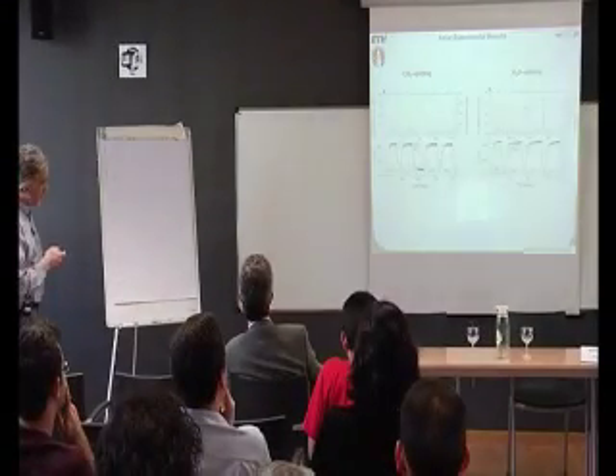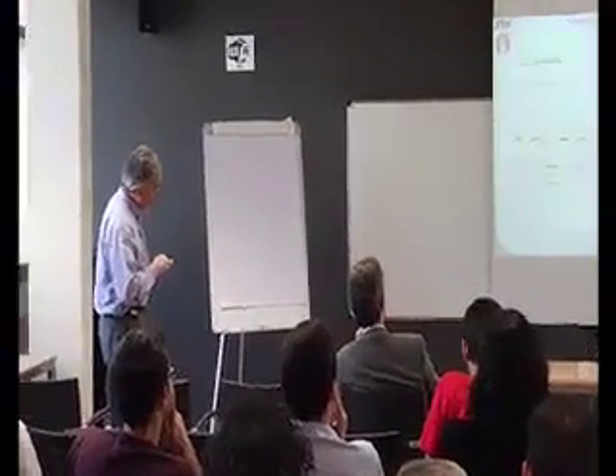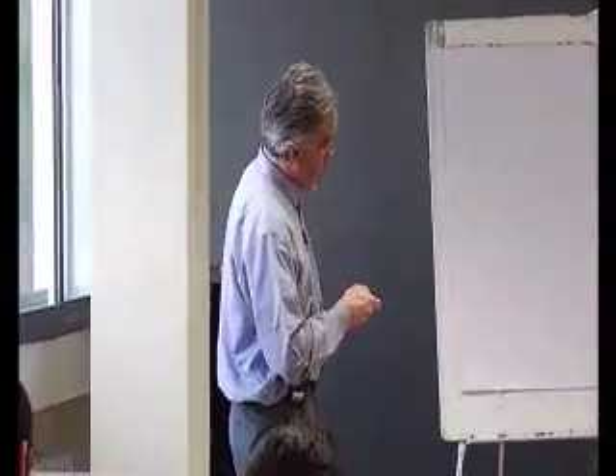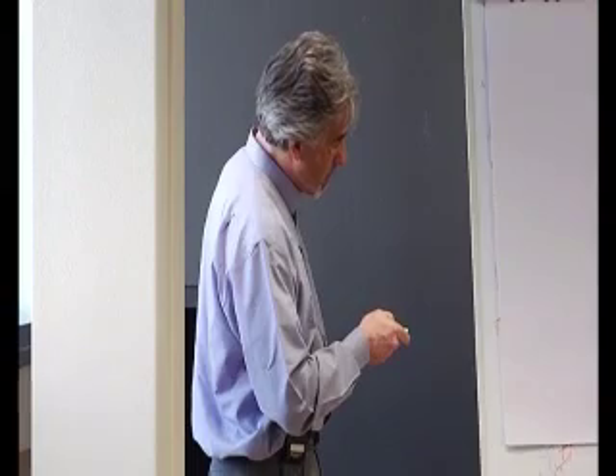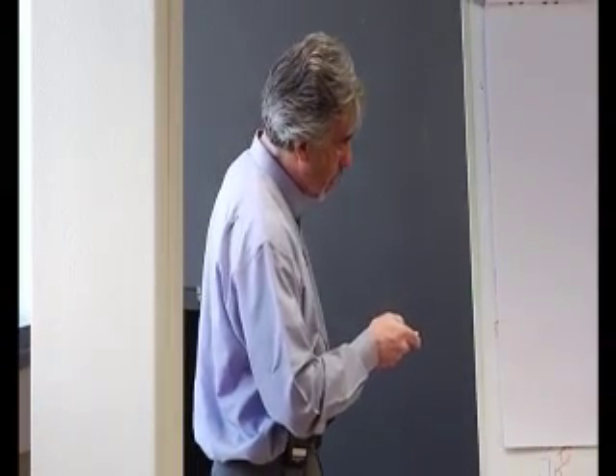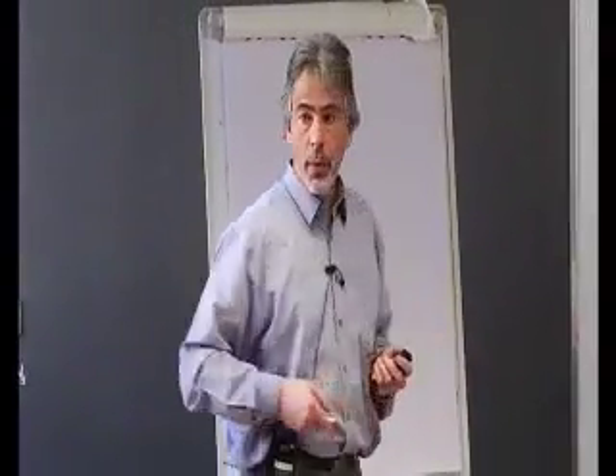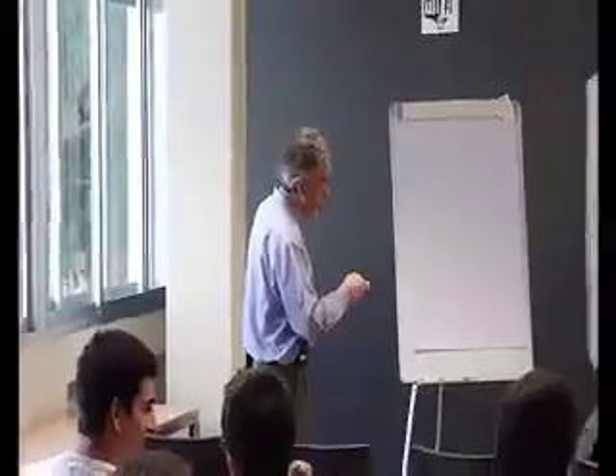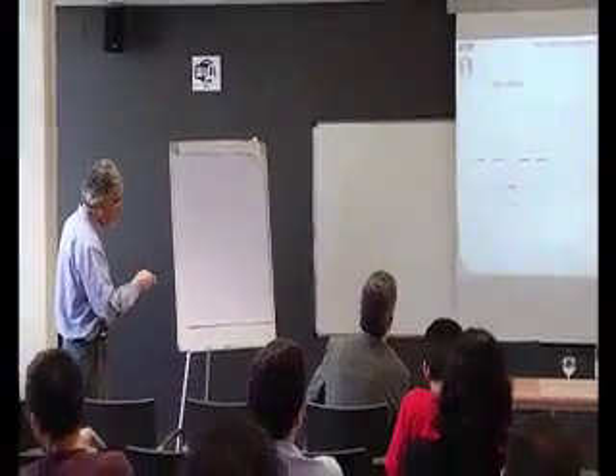Now, here you see the results of the experiments. On the left side is the CO2 splitting. The lower curve is showing the temperatures of 4 consecutive cycles. A reduction at around 1600 Celsius, oxidation at around 900 degrees Celsius. And then again reduction, oxidation, reduction, oxidation. And on the top graph, you see the composition of the gases at the outlet. Here, we analyze the gases by gas chromatograph. And here you see during the reduction, the oxygen peak. During the oxidation, CO2 to CO, the CO peak. And then again, oxygen, CO, oxygen, CO, oxygen, CO. 4 times.